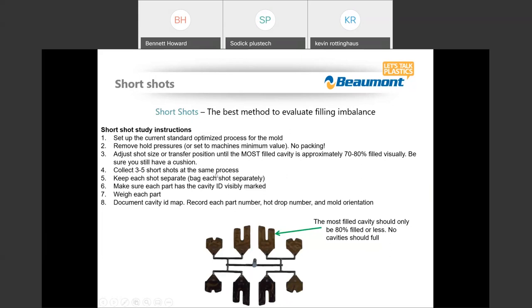The reason I specify that same process is that sometimes, in order to gather our short shots or identify where they are in the tool, we have to stop the mold and pick them up by hand so we know their position within the tool, because sometimes we can't identify our cavities, as the cavity ID might be at the end of fill and it's not there. So we might have to write these numbers on the part as they come out, tape them, however you have to do it in order to identify where they are positionally within that tool.